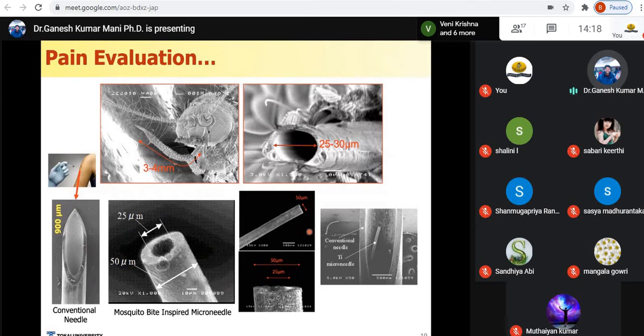After the sputtering, we etch and remove the copper wire, so that you get this hollow structure, which is almost similar to the mosquito's labium. Here you can see the comparison of the commercial needle and the titanium microneedle. So we fabricated the microneedle. As I was telling in the first step itself, it is a painless microneedle.